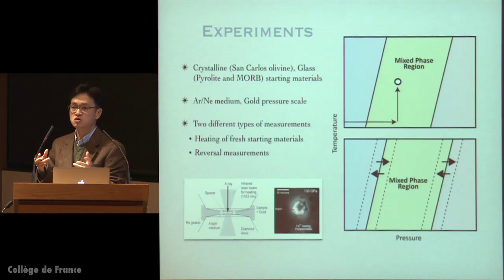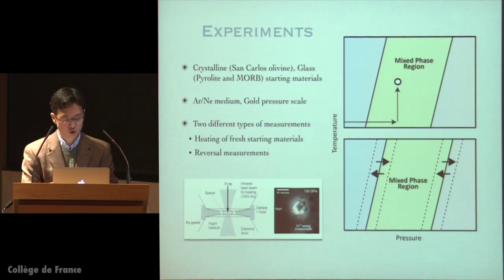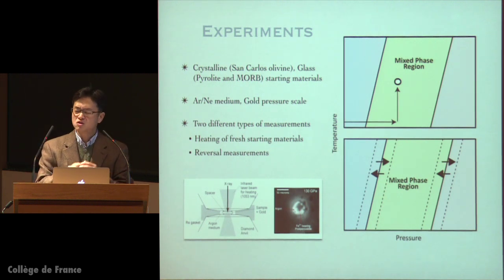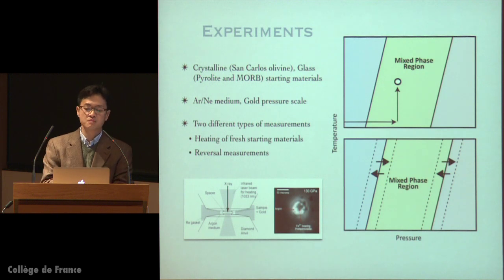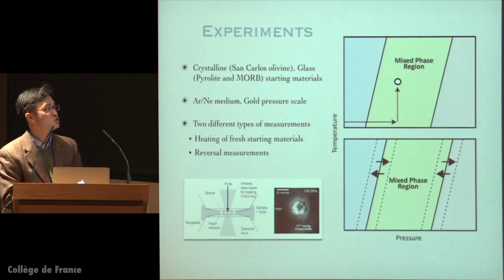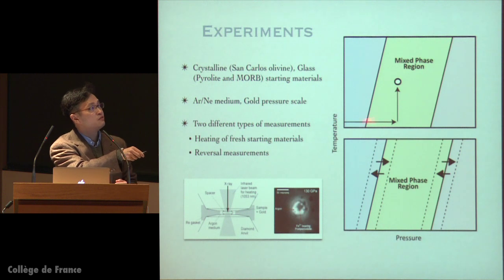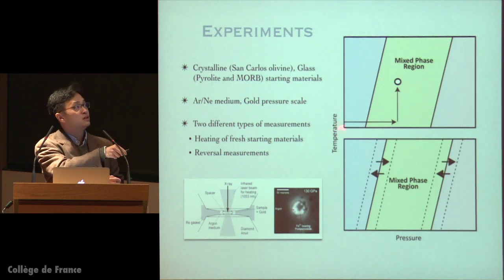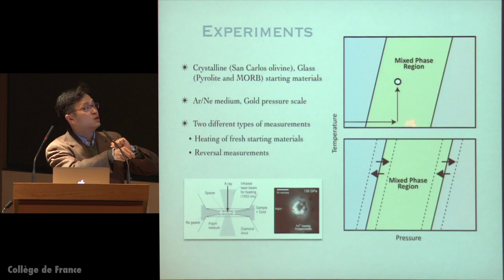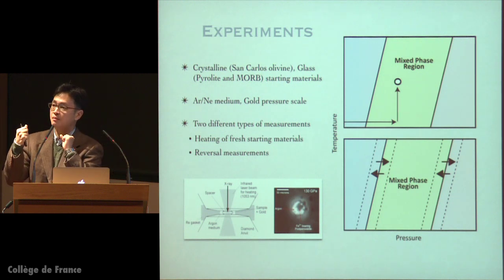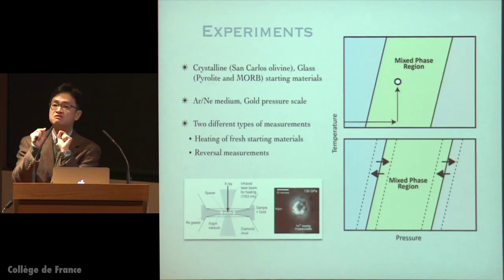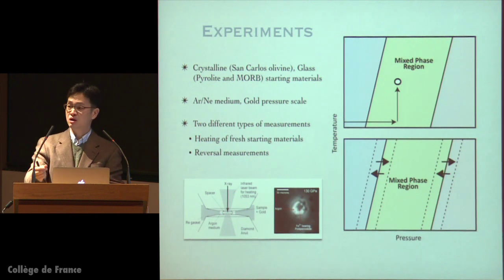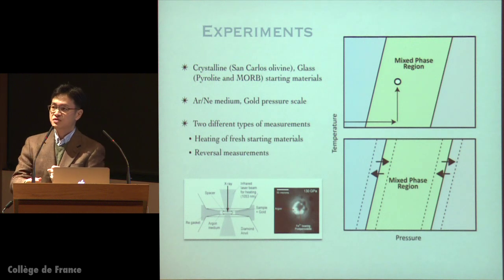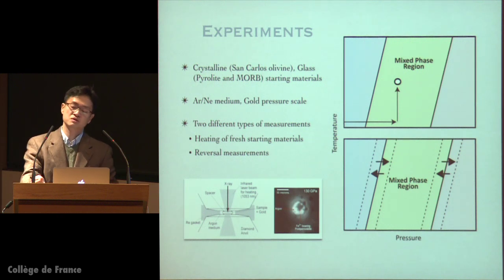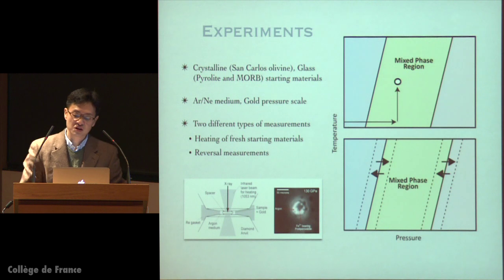Then we got interesting discussions with other groups who also worked on this issue. And traditionally, over megabars of pressure, because of a lot of limitations, people have used a different method where they actually bring the fresh, unheated sample to a certain pressure range and then heat it up and then look at what type of phase is formed. So the advantage is that because you start with very unstable starting material, there is a hope that it goes into the stable assemblage better than in other cases.